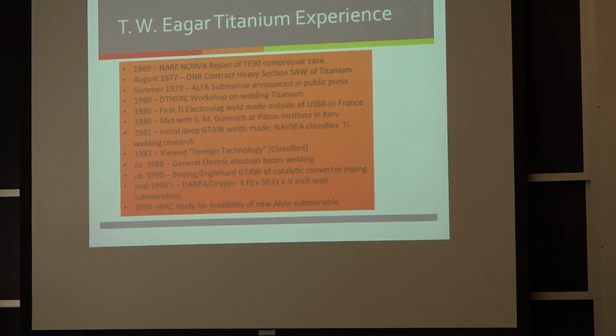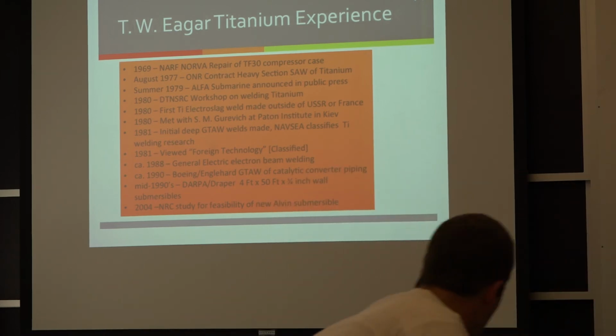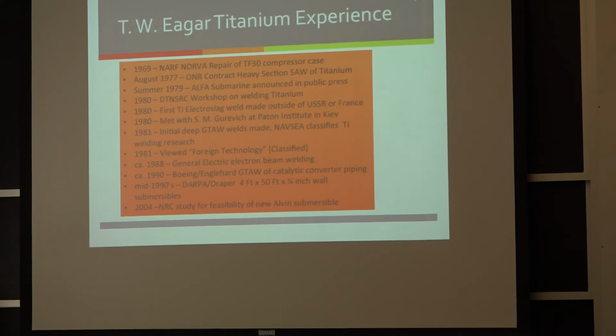I had a research contract to do resistance spot welding in the mid-80s with these guys. And one of their engineers calls me up and says, Tom, can you help us, we have a problem welding titanium. I listened to him and said, Lyle, when you clean it with acetone, I told you you have to use white gloves, and they were using white gloves. I said, when you use acetone, you've got to use reagent grade acetone, because most acetone has a little bit of grease in it, unless it's reagent grade. When you clean with it, there will be a thin film of grease on there, and that grease is going to introduce hydrogen, which introduces porosity into your weld. You've got to use reagent grade acetone.